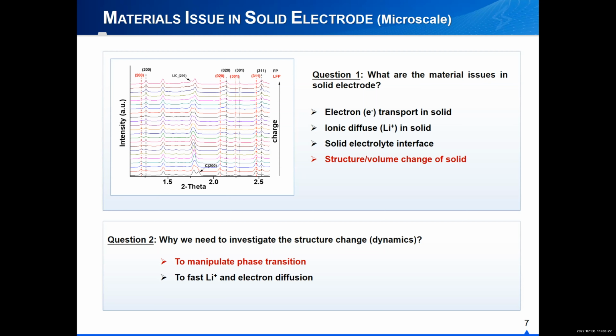So that'd be question 2. Why do we need to investigate the structure change? We just try to manipulate the phase transition and to speed up lithium ion and electron diffusion. Okay. This is typical in situ XRD data from lithium iron phosphate during the charge process. So take the 200 plane, for example. The red one is lithium iron phosphate and the black one is iron phosphate. And during the charge process, the intensity of lithium iron phosphate continues to decrease, while the iron phosphate continues to increase. So this is a typical two-phase reaction, right?